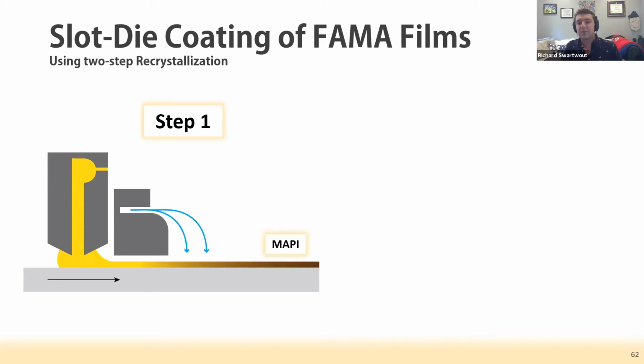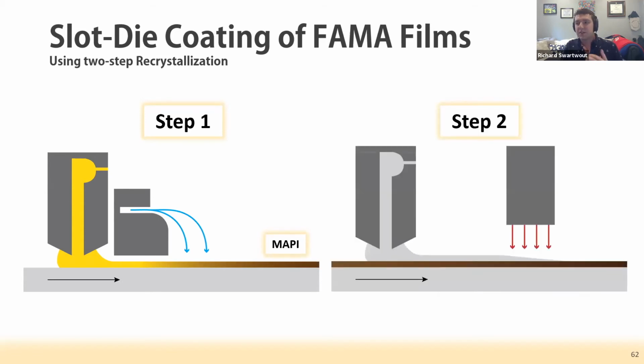For the second step, we take this carboxylic acid based ink, coat it on top of the methylammonium lead iodide film, and then immediately dry it with a heated air knife. This simulates how this would work at scale with a forced air annealing oven.